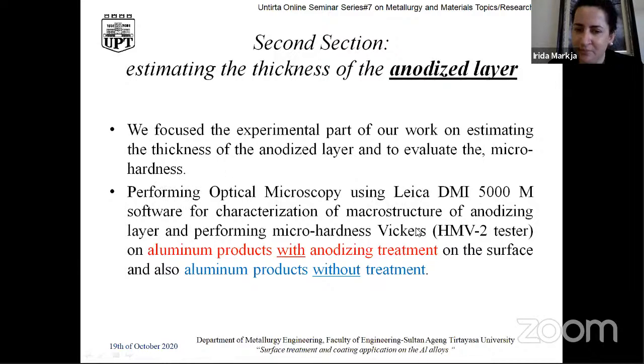And micro hardness Vickers we have performed on aluminum products with anodizing treatment on the surface engineering, and on aluminum products without treatment. For sure, we have taken the samples at different elongations of the aluminum profile, in different sections, to see the anodizing process during the whole profile, and the homogeneity of the process at different points and different sections of the profile or of the surface engineering, because we should have an